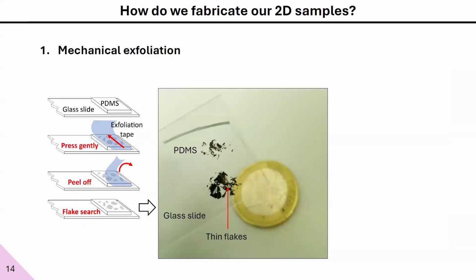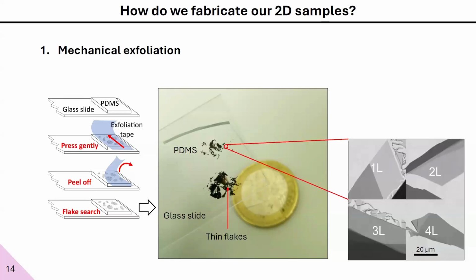We use this method, and basically we take this piece of tape with thin 2D materials and stamp it on a transparent substrate, which you see here. We use a transparent substrate because we will then use it for good alignment and a deterministic placement of our flakes on our desired substrate. If you look under the microscope, you can find these beautiful tiny pieces of atomically thin flakes.